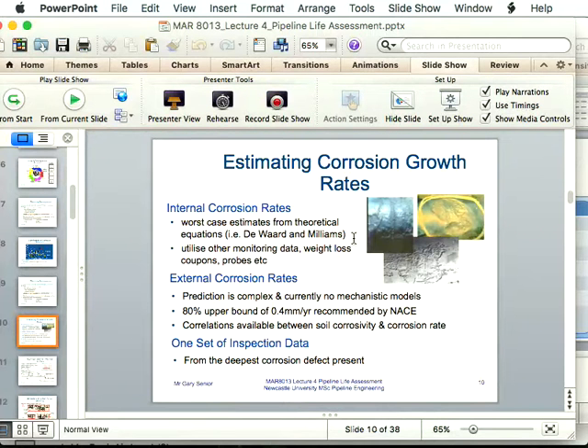And then external corrosion rates is the next group of bullet points. There are definitely no absolute theories out there on how to do it, but NACE, which is referenced there, is the Corrosion Society in North America. They've got masses of correlations of data of different rates, because the corrosion growth rate isn't constant during the pipeline's life. The corrosion rate in its early growth phase is quite low, then it accelerates, and then it drops off as the corrosion gets almost through wall. It then starts to create a layer in the corrosion that stops the water getting in, so it plateaus off.